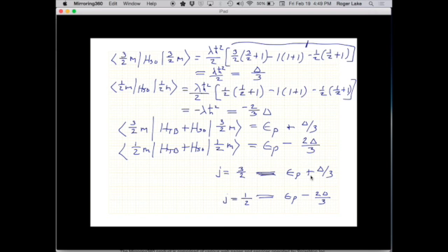So these 4 states here will become your light hole and heavy hole bands. Your 2 bands with 2 spins each, right? Because your 3/2 state can have m equal 3/2, 1/2, negative a half, and negative 3/2. So there's 4. You can't think of it as spin up or spin down anymore.